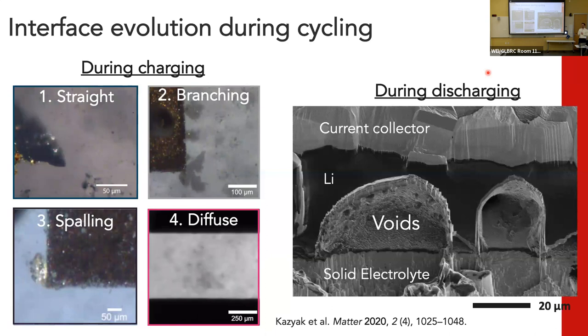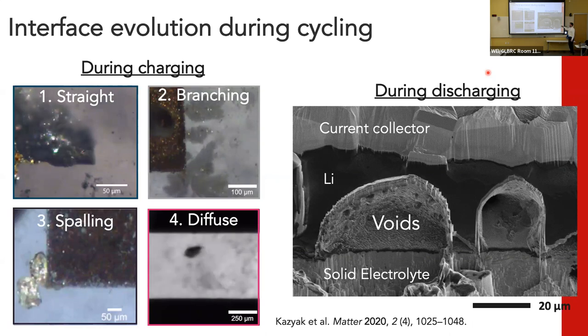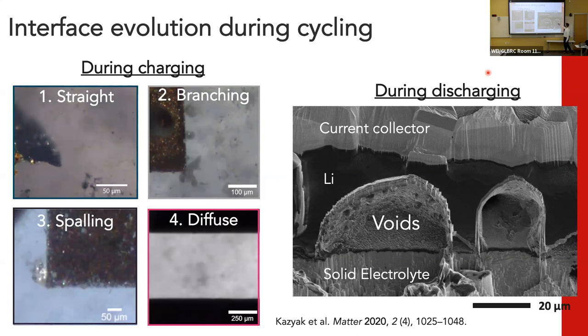Now, maybe it doesn't have the catastrophic consequences of a very bad fire, because it's a non-flammable electrolyte now, but this still kills your battery. So we need to prevent this from happening. This is during discharge instead of charging. You can lose contact between your planar lithium electrode and your solid electrolyte. Here you get these big voids, which decreases your interfacial area and causes all kinds of problems.